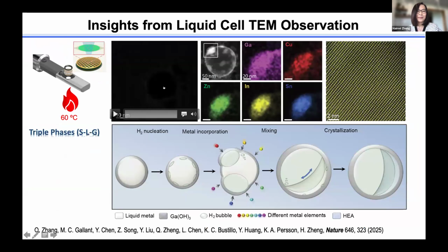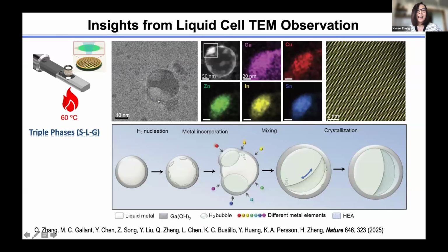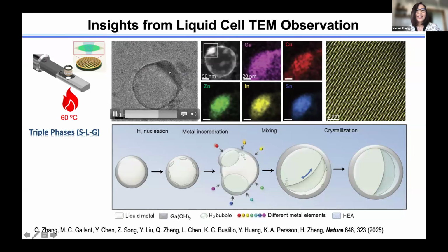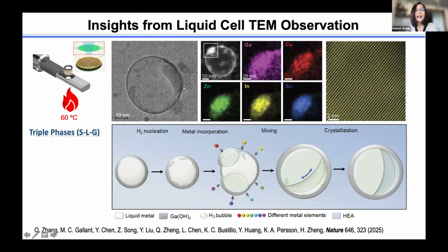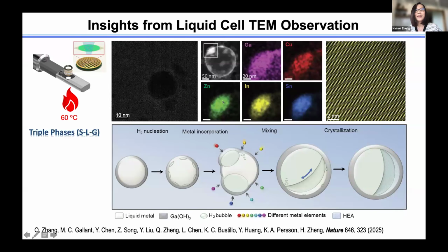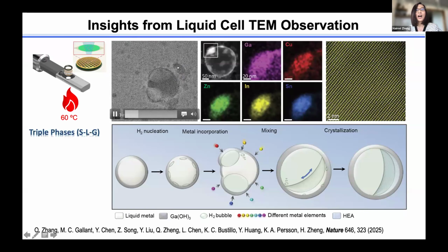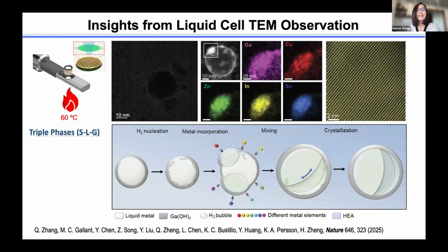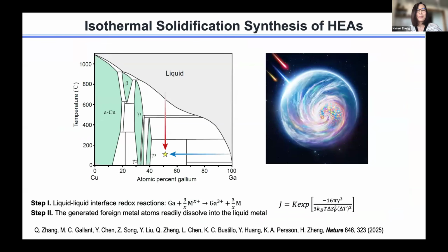And this is the liquid cell TEM experiment. We use the metal alloy here, and then we put in the ion solution of copper. We found interesting, fascinating dynamics. It has gas and it has solid and liquid. Eventually, it solidified. Remarkably, we found the copper ions get inside this liquid metal. And this is very inspiring. It gives us a very important clue.